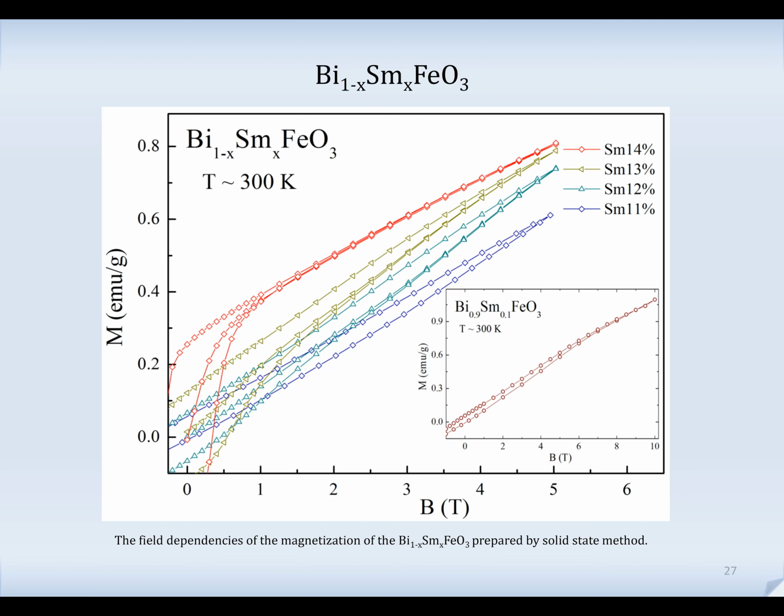The remnant magnetization is really small because we still have an anti-ferromagnetic structure. But this small magnetic moment is caused by non-collinear, not perfectly collinear orientation of magnetic moments. So we have some non-zero, but really small, magnetization. And it's understandable for us. So if we have R phase, we have nearly zero. If we have O phase, we have released magnetization.